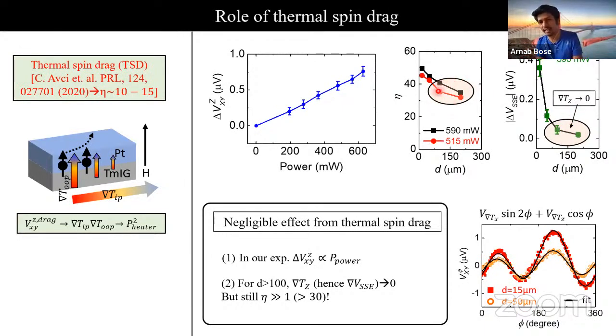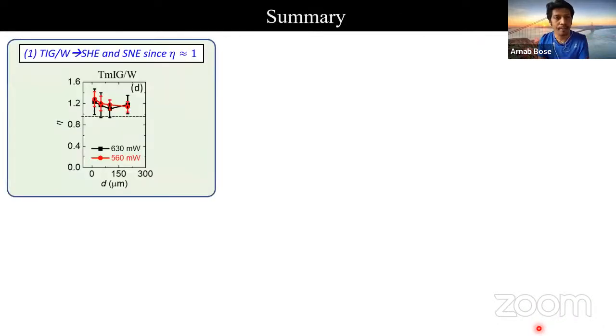But still, even in that case, the value of eta is substantially different than 1, even when the out-of-plane thermal gradient is negligible. So again, this cannot explain it. It suggests that our data cannot be explained by the proposed thermal spin drag mechanism. Now let me summarize. We report the unambiguous detection of the spin Seebeck effect in TMIG tungsten, which results in a value of eta very close to 1 within our experimental uncertainties.